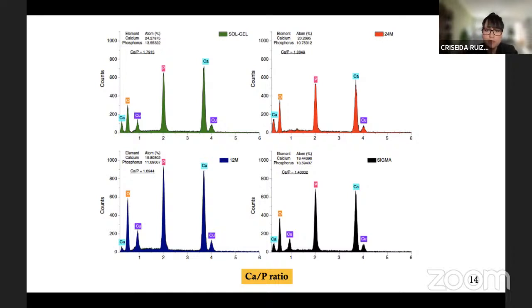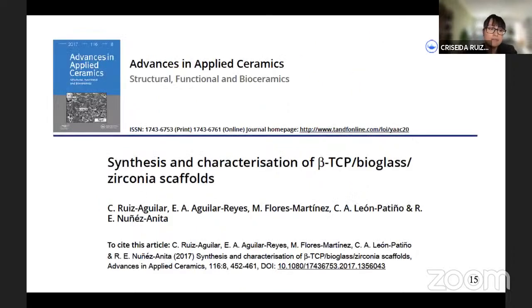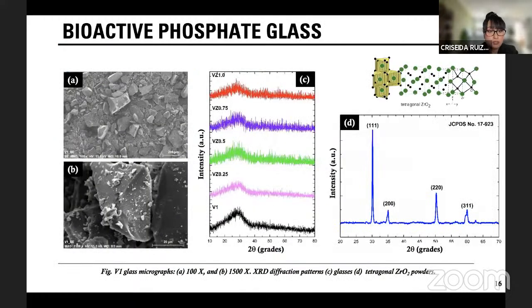Some studies have presented bioactive glasses doped with different elements to improve mechanical properties and reduce the dissolution process. Nevertheless, several compositions of bioactive glasses were manufactured doped with zirconia, or zirconium oxide, to improve the dissolution properties and the cell interaction in this investigation.